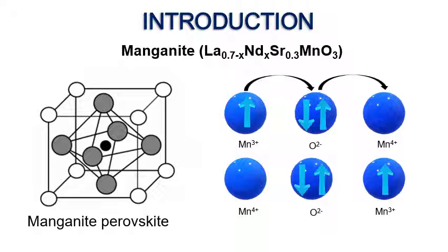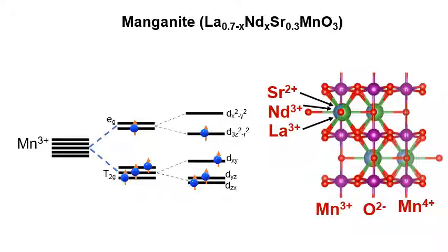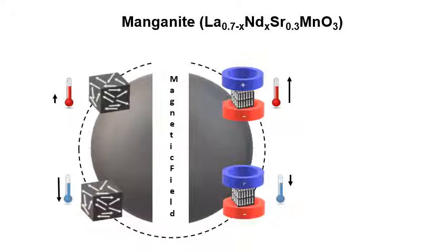The manganite system bases its foundation on different interactions. One of the main ones is double exchange, super exchange, and direct exchange between the ions of manganese and oxygen. This classification is correlated with the general rules of Goodenough, with which the sites and the interactions can be predicted. The magnetocaloric effect is defined as the isothermal magnetic entropy change or adiabatic temperature change of a magnetic material upon application of a magnetic field.